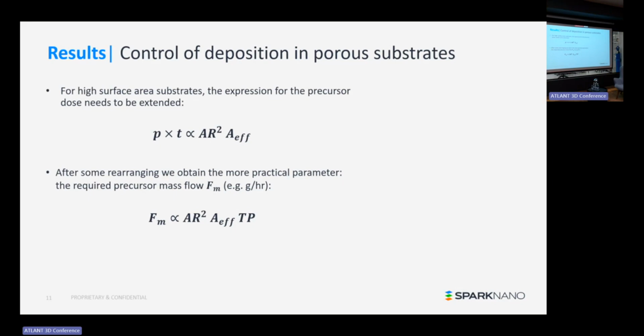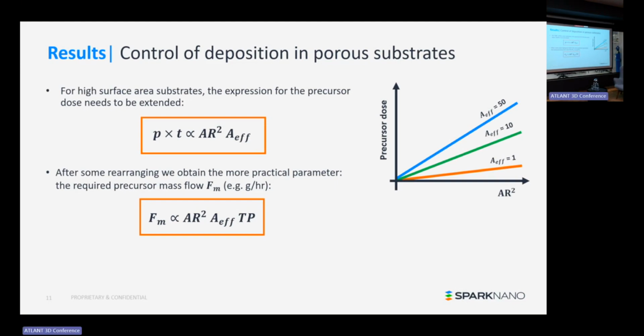That's fine. So for high surface area substrates, the expression for the precursor dose actually needs to be extended. It's not only dependent on the square of the aspect ratio, but also on the effective surface area. So what does this mean? Here you can plot the required precursor dose to conformally coat all your pores as a function of the aspect ratio squared, which is then of course a straight line. But if you do that for several different effective surface areas, even though at this point here the aspect ratio in all cases is the same, we do need to increase the precursor dose just because of the enhanced surface area. So what does this mean?